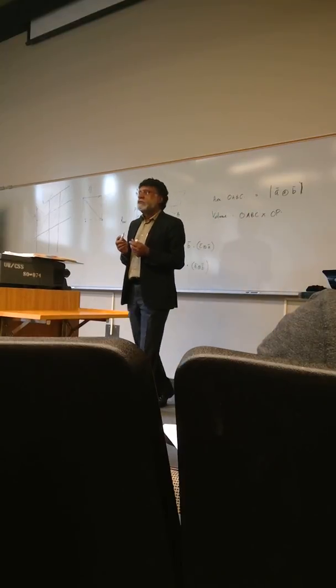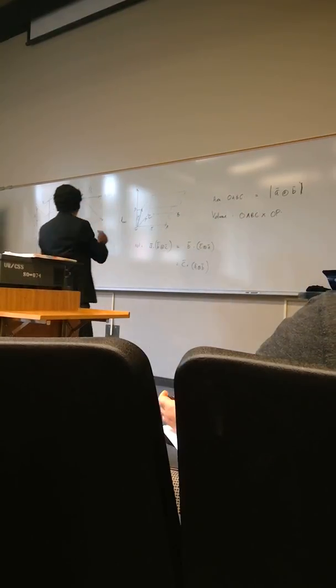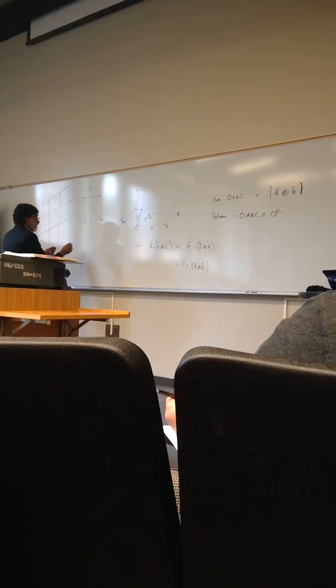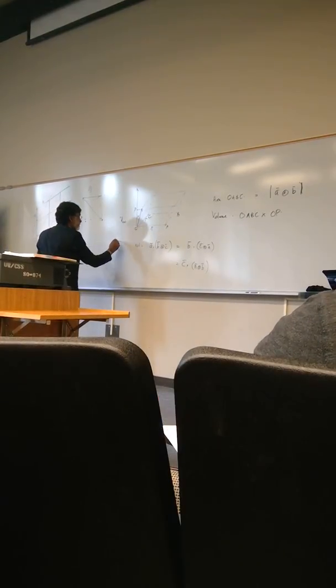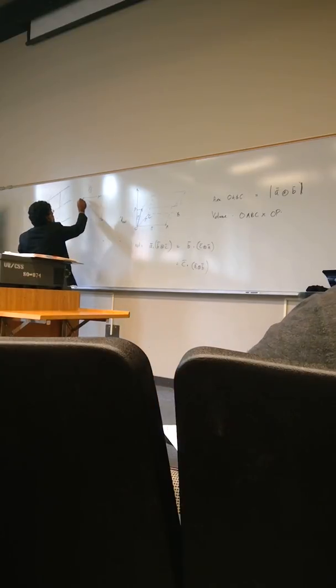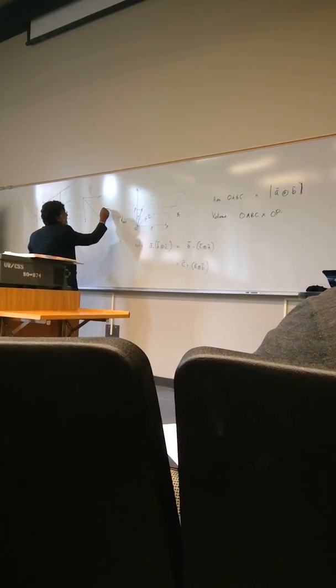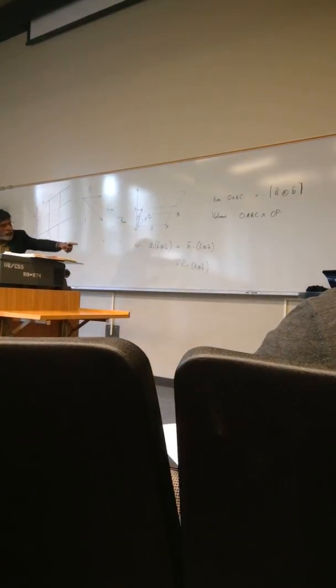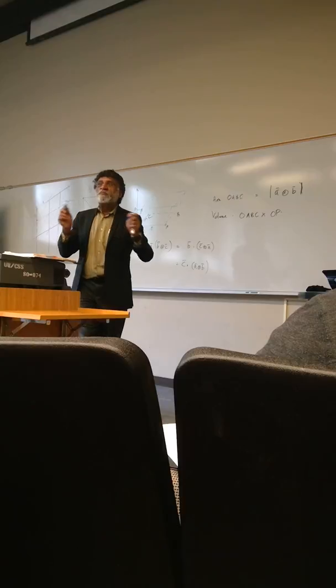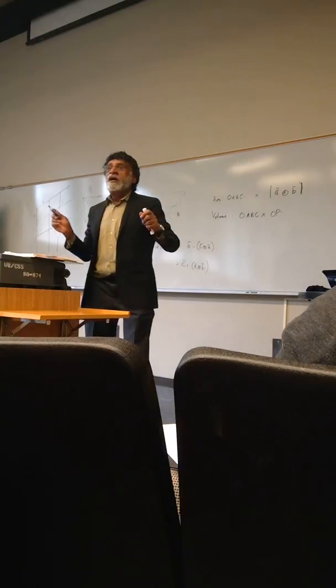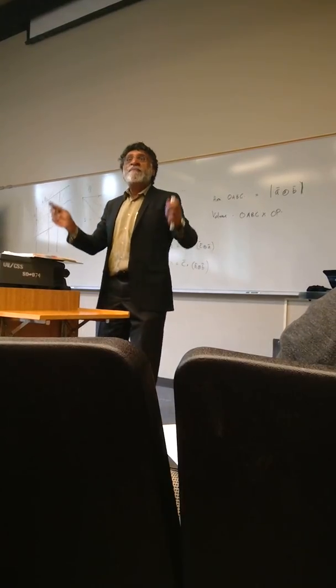So any vector here, if you have this reciprocal lattice, see, this is the lattice now, we have points. You can take this vector, this would be your G, H, K, L, given by H times A star, K times B star, and L times C star, and you can write any vector, it's a lattice. Each of these points represents an entire family of planes.